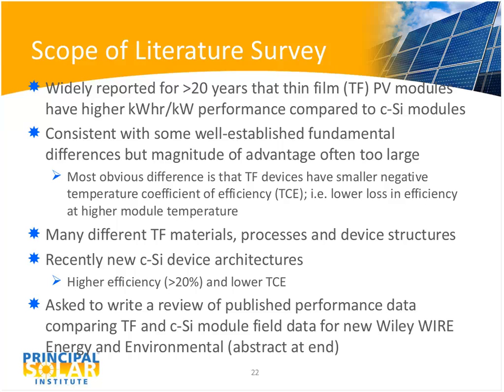Now, it's really not fair to lump together all thin films because there's different materials, different processes, different device structures, and some authors do that, and it's really not fair because they are different and they do have different parameters. But also recently, some of the new high-efficiency advanced crystalline silicon device structures, like the HIT cell from Sanyo and the back contact cell from SunPower, also have lower temperature coefficients than standard crystalline silicon. And so they also fall into this area where they might be expected to have, and in fact have been shown to have, higher kilowatt-hour performance.